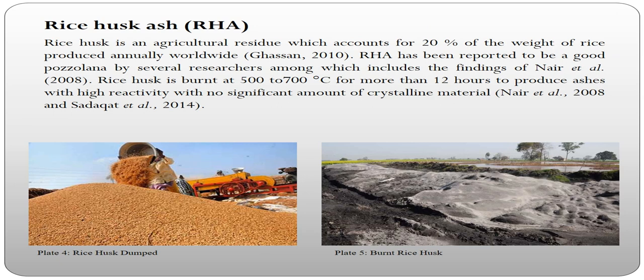Rice husk ash. Rice husk ash is an agricultural residue which accounts for 20% of the weight of rice produced annually worldwide. Rice husk ash has been reported to be a good pozzolana by several researchers, among which include the finding of Nair et al. Rice husk ash is burned at 500 to 700 degrees centigrade for more than 12 hours to produce ashes with high reactivity with no significant amount of crystalline material.